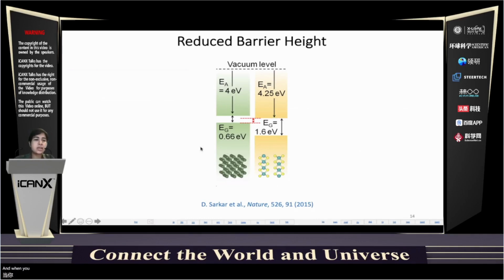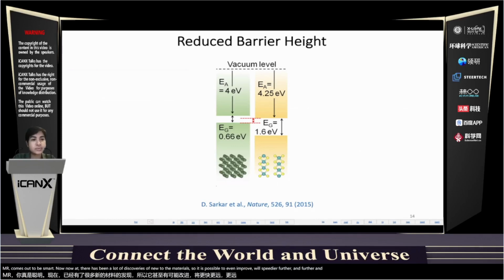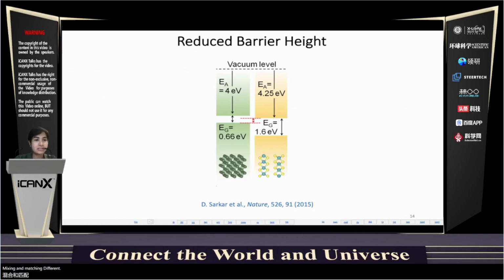And when you align the bands, we will see that the height of the barrier, which is defined by the energy difference between the conduction band of molybdenum disulfide and the valence band of germanium, as shown by this red arrow here, comes out to be small. Now there have been a lot of discoveries of new 2D materials. So it is possible to improve the barrier height further and optimize our design by mixing and matching different kinds of materials. So there is a lot of opportunity for improvement.